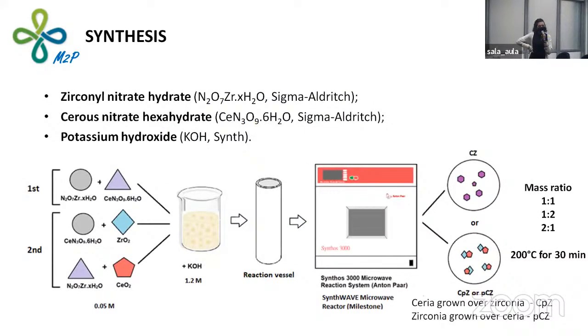Here I start showing the synthesis, and we use the microwave hydrothermal system. In the first path we took, we mixed the cerous nitrate hexahydrate with the zirconyl nitrate hydrate to form the solid solutions that we referred to as CZ. In the second path, we first synthesized zirconia and ceria, then zirconia was mixed with cerous nitrate hexahydrate, while ceria was mixed with zirconyl nitrate hydrate. They then passed for another time in the microwave, forming the CPZ and PCZ that were ceria grown over zirconia and zirconia grown over ceria. We used the mass ratios of 1:1, 1:2, and 2:1, and the synthesis was carried out at 200 degrees for 30 minutes.